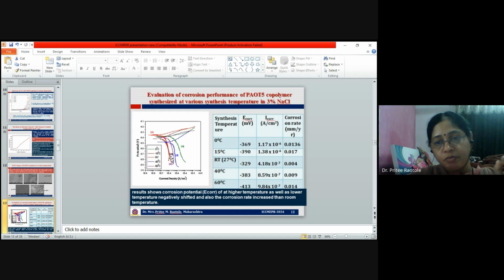The corrosion protection performance of PAOT5 copolymer synthesized at various synthesis temperatures in 3% NaCl was evaluated by potentiodynamic polarization measurement, and these results show that the corrosion potential at higher as well as lower temperatures shifted negatively, and also the corrosion rate increased compared to that at room temperature. So it indicates that the corrosion resistant characteristics of the coating are better when it is synthesized at room temperature.